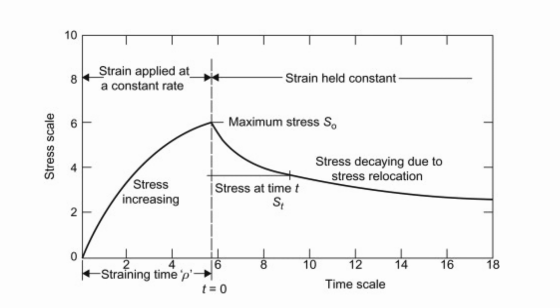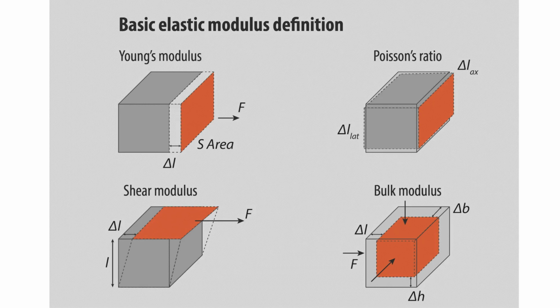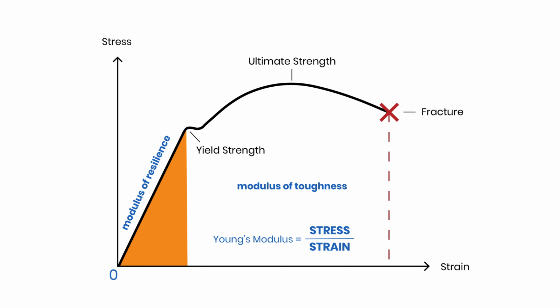It is the tensile stress relaxation modulus if the corresponding strains and stresses are tensile. Alternatively, if the strains and stresses relate to shear or hydrostatic changes, then the corresponding material parameters are the shear and bulk relaxation moduli, respectively. For polymers, the tensile modulus should not be referred to as Young's modulus. Young's modulus is the limiting case of the tensile modulus, when the induced strains can be considered infinitesimal and independent